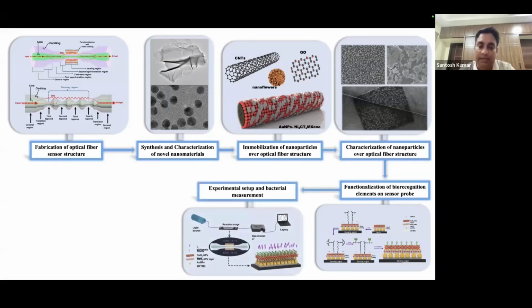So this measurement process is very easy and not expensive. We use a tungsten halogen light source in the range of 200 to 1000 nanometer, and the spectrometer is in the same range. And we connect that with the reaction stage, a homemade reaction stage we have prepared in our lab, and the spectrometer can connect with the laptop. Here reaction stage means that our developed sensor is connected with the fusion splicer, light source and spectrometer, and then we do the detection process.